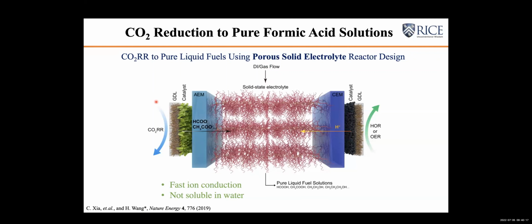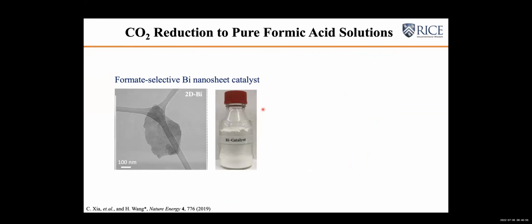In this case, as you can see, CO2 gets reduced on a formate-selective catalyst, forming formate, which crosses over the anion exchange membrane into the middle layer of solid electrolyte. At the same time, water gets oxidized, or hydrogen, whatever reactant you want, releasing protons that come through the cation exchange membrane into the middle layer of solid electrolyte. So this formate and proton will meet and recombine to form pure formic acid molecules that can be flushed out by the DI water to get high purity liquid fuels.